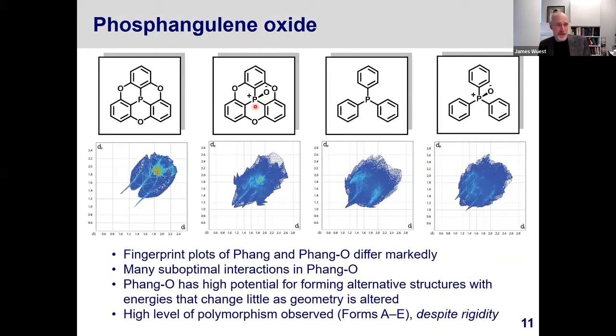This unhappiness is illustrated by looking at the fingerprint plots of the Hirschfeld surfaces. And you can see here for phosphangulene that it has a very characteristic, rather compact fingerprint that indicates that the interactions focus on the type of interactions you would have in a stacking of aromatic surfaces with CHO hydrogen bonds. If you look at the phosphangulene oxide fingerprint plot, you can see that it's much more extended, and there's a high density of points that lie at rather large interatomic distances. Which is an illustration of some degree of unhappiness of the structure. It can't find anything that's particularly suitable, and this is the best that it can do.